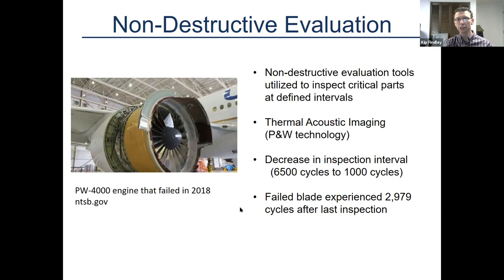So this particular blade that failed in 2018 experienced almost 3,000 cycles after the last inspection. They thought it could go up to 6,500, but apparently it couldn't. Based on this, that's when they started reducing the inspection intervals on these blades.